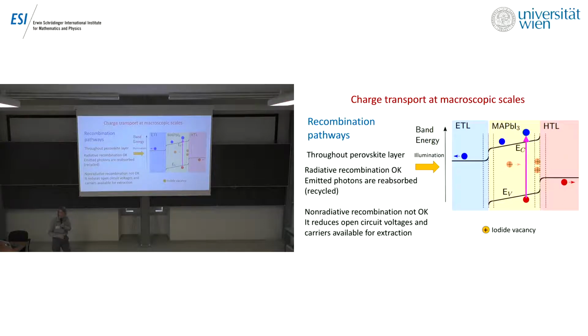So Jarvis mentioned recombination. Why do we care about recombination? The answer is because we want our solar cell to work. The way solar cells work is you excite an electron across the band gap to create an electron-hole pair. Because in the case of perovskites you've got this very high dielectric constant, the exciton formed very quickly dissociates, and you get the free charges moving out of the cell in different directions to create a current, and on the way out of the cell, they can recombine.